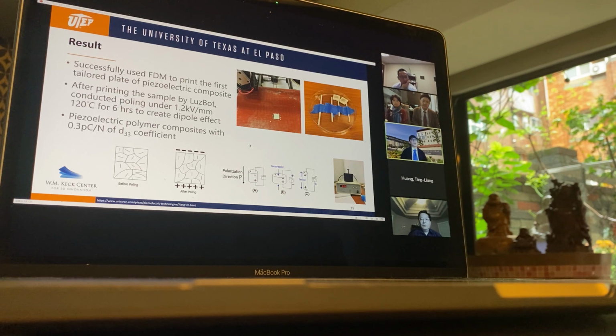So after printing out the plate-like product, we did the poling process under 1200 volts per millimeter for 6 hours to obtain the dipole effect in the sample. So the poling process is demonstrated beneath this slide.